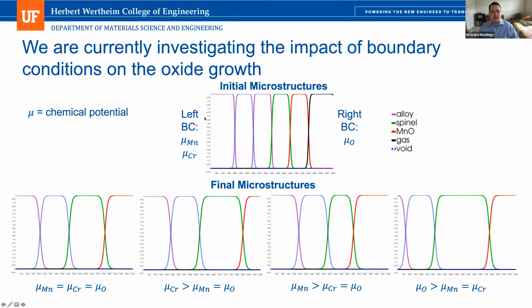And we're setting boundary conditions. So on the left, we're allowing manganese and chrome to enter the system. And on the right, we're allowing oxygen to enter the system. And we're defining that in terms of a set chemical potential on the boundaries. And when we set the chemical potential of all manganese, chrome, and oxygen to be equal, then first off, the void grows and actually overtakes this secondary metal phase. And so we end up just having a void in between, right on the oxide metal interface, which is what we've seen in the experiments.